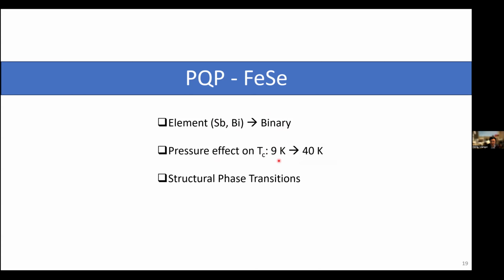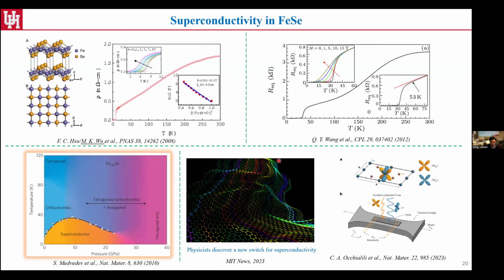At ambient condition, the TC is only around 9 Kelvin, but once you add pressure, a few GPa, it boosts up to 40 Kelvin. So that's a huge enhancement. And more importantly, as I mentioned, we're thinking about taking advantage of the energy barrier. And then the follow-up question would be, what provides those energy barriers, right? One naive thought is those first order structural phase transitions that normally come along with a considerable amount of latent heat, and that can help to lock in this phase. So that's why we come to iron selenium, and this material has continuously provided a lot of interesting physical results and insights.